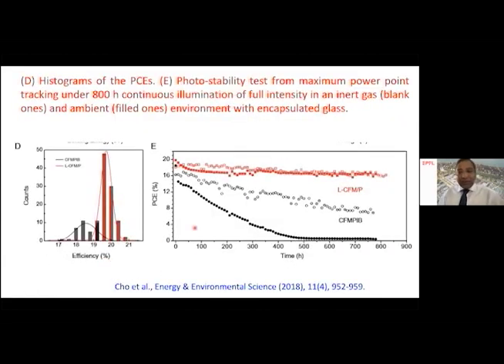Now, if you look at the importance of this interface engineering, just take focus on the stability data measured by using maximum power point tracking up to 800 hours. Just focus on the open squares. Open squares are the layered perovskite solar cells, that's a two-dimensional perovskite deposited on top of three-dimensional perovskite, measured under argon atmosphere conditions. You can see the stability is intact.